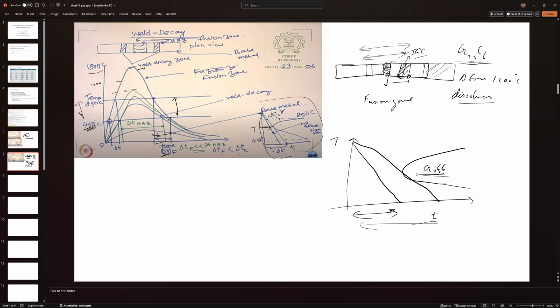However, if you see this plot, this blue one, you never reach a temperature above 850 degrees Celsius. So right when you cross 450 degrees Celsius the first time, the chromium carbide precipitation starts, and the temperature increases and falls back during welding.